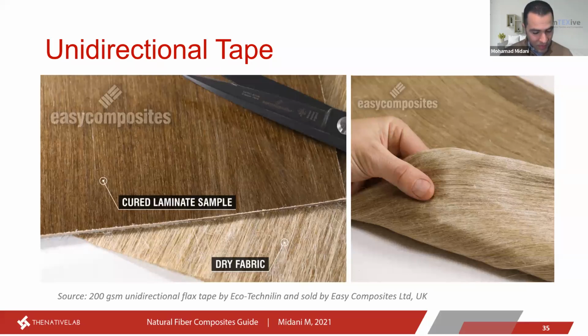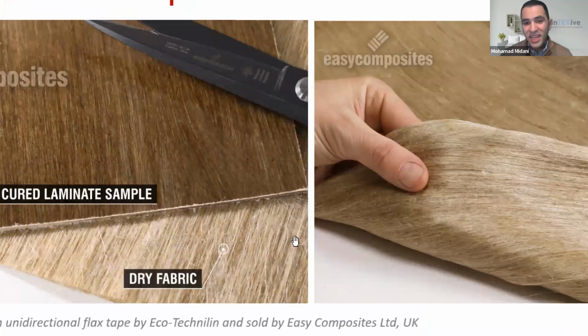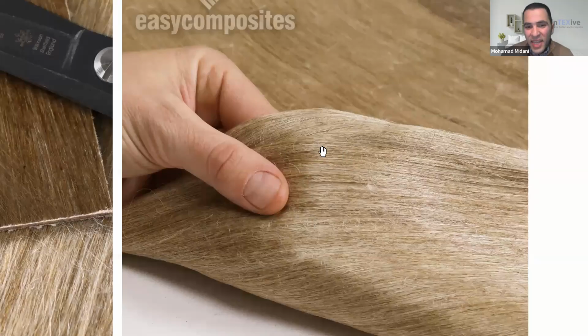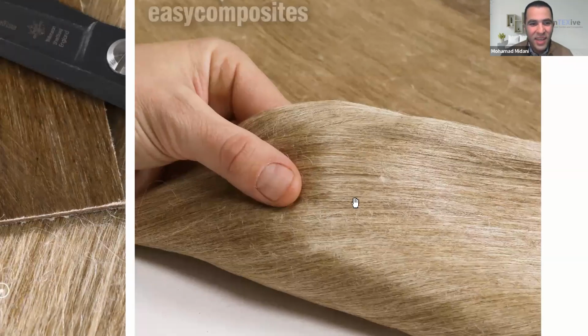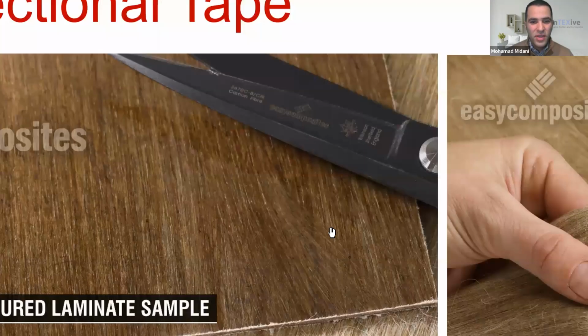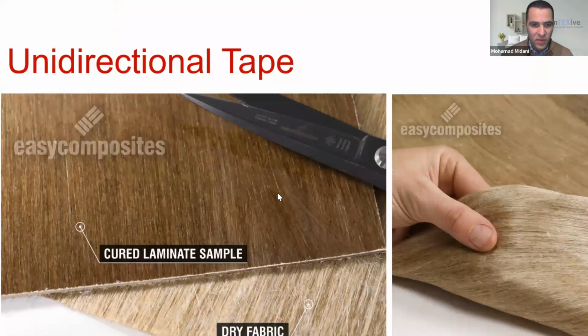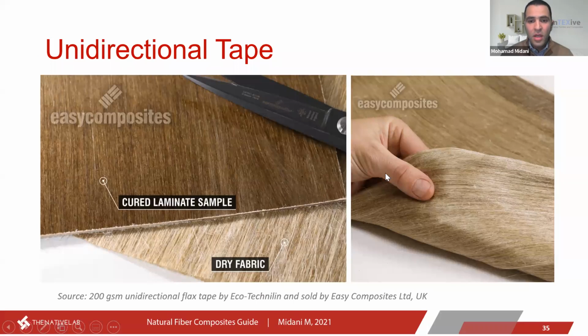But the only limitation, I would say, is that they are delicate. They need to be handled with care. It's very easy to distort during handling. So you can see here, for instance, there's part of it that is distorted because there's nothing holding those fibers except for the interfiber friction and some adhesion forces between the fibers. These are also made of flax, 200 grams of flax.